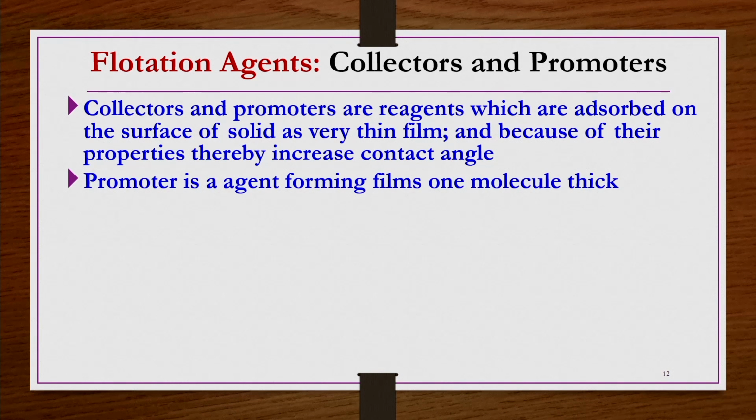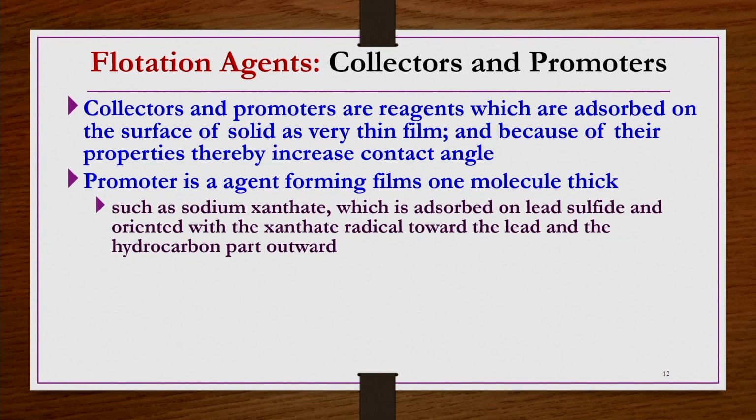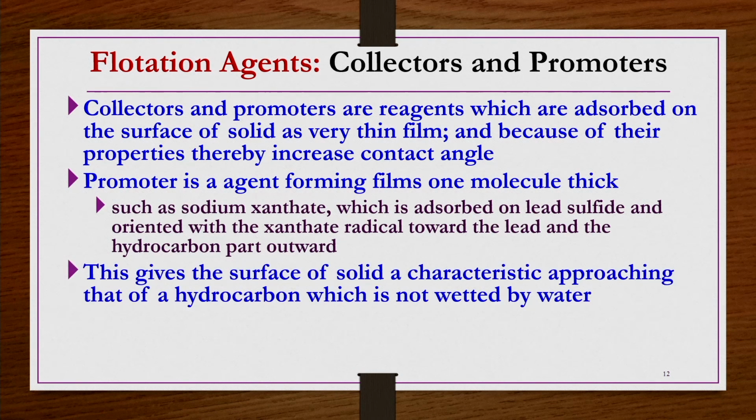A promoter is an agent forming films one molecule thick in general, such as sodium xanthate, which is adsorbed on lead sulphide and oriented with the xanthate radical toward the lead and the hydrocarbon part outward. This gives the surface of a solid a characteristic approaching that of a hydrocarbon which is not wetted by the water. If that is not wetted by the water, that will be easily wetted by the air bubble, and then can be separated as an overflow from the top of the flotation cell or flotation equipment.